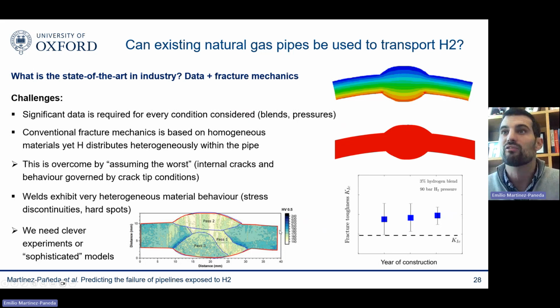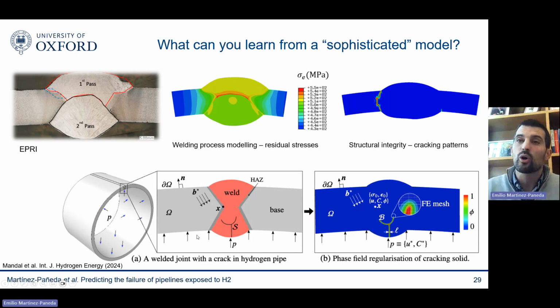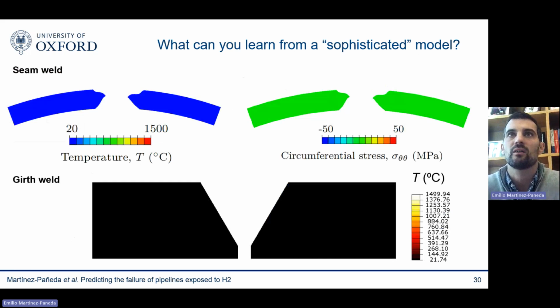But the problem is that the welds are going to fail before the base material, and this does not work in welds because, again, you have a heterogeneous material behavior, and you're not able to characterize what the fracture toughness of the heat-affected zone is. So that's the challenge. So we hope to overcome this challenge by using this sophisticated model, so to say. So you have a simulation where you do the weld process modeling, and then you use this model I showed you before to predict the critical pressure at which the pipe will fail.